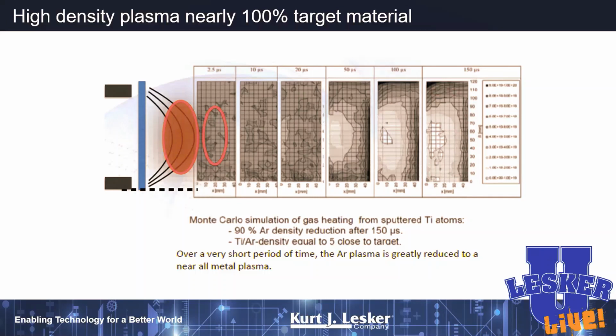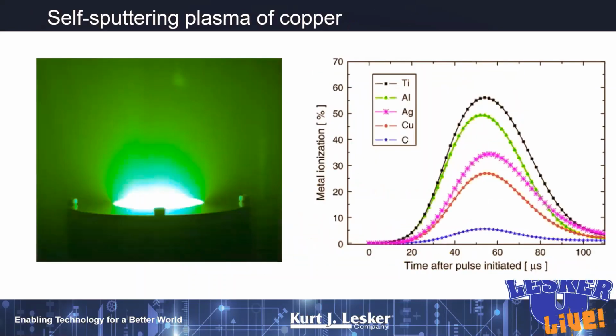And at this point, we can reduce the contribution of argon in the chamber. By doing that, we're going to have much more pristine films with fewer gas inclusions, much more energetic films, so our films are going to be more dense. This is just an image of copper self-sputtering. Notice that there's none of the characteristic purple that you would see from an argon plasma. It is completely dominated by copper metal ions.